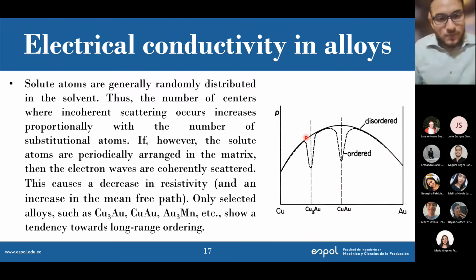Now, what happens if I have a periodic arrangement? It's difficult to get, yes, but I can get it. And we know of many alloys that have a perfect arrangement of atoms. If I have an ordered matrix, or a nice order between solute atoms and the matrix, then my microstructure will not be disordered, right? What happens? Then I have a periodic arrangement, so I have the nice AB, for example, or the ABC. Then those electron waves will be coherently scattered, even though I have solute atoms, because of that arrangement.